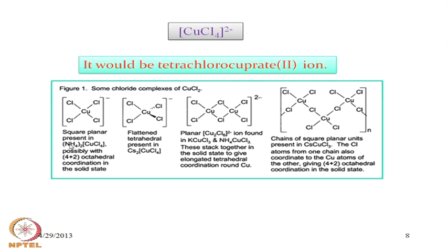So, the ammonium salt would be crystallizing as the corresponding species which would be octahedral in the solid state through sharing. But if we try to crystallize it as its corresponding cesium salt, this would also be 2 minus only. So, Cs2CuCl4, which is cesium tetrachlorocuprate, but this time the structure is different because of the presence of this cation, because the size of the ammonium ion is small.